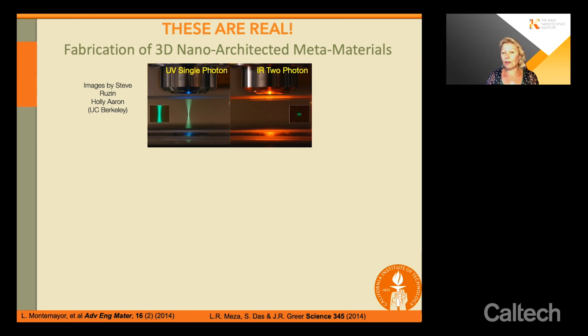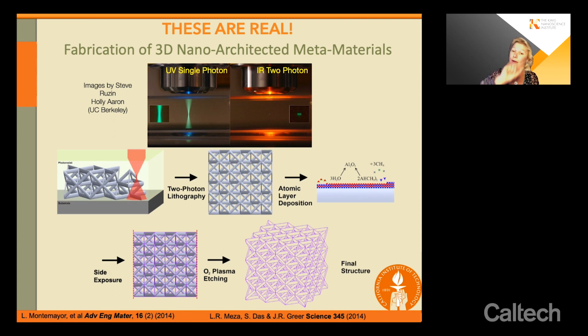We use this technique called two-photon lithography, where it's possible to focus the laser light in a single voxel, and you can see how small it is. And that allows us to sculpt by rastering this voxel in the three-dimensional space to write whatever image you want. We're not limited to periodicity, and there's no mask that's used in this process. In fact, if I could see all of you, I could write a nano version of each one of you. Now, this reaction that creates these scaffolds is all done using laser light photoinitiated polymerization. So these are polymers. Now, of course, we're not going to only work with polymers, right? We're a truly material science lab.